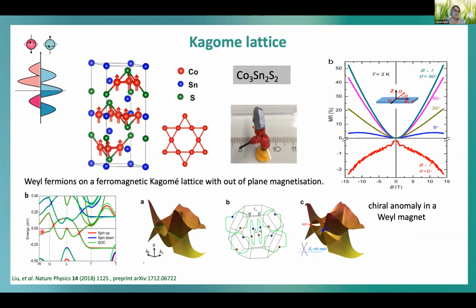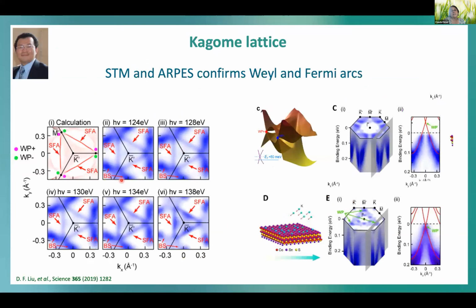But anyway, at the Fermi energy, this compound—a shandite, even a natural compound—has a semiconducting relative with 1 electron less. So you simply fill in 1 additional electron, filling 1 band. These crossing bands, the 2 crossing bands, then you get this nodal line if you have no magnetic field. But if you apply a magnetic field and magnetize your crystal, you see these Weyl points, which are much farther from each other compared to niobium and tantalum arsenide, and on top are very close to the Fermi energy.